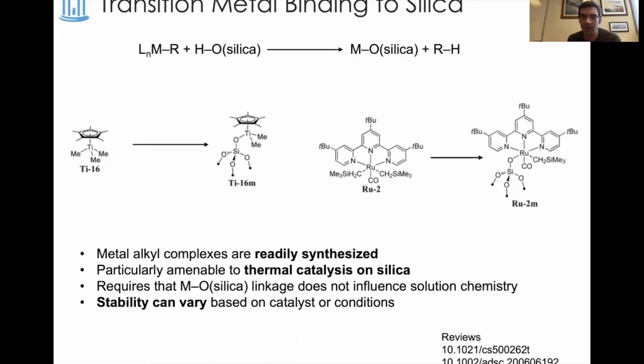The drawback, or potential drawback, is that you need this ligand that's now directly bound to the metal to be amenable to the chemistry that you're interested in. So if your catalyst tolerates an alkoxide ligand in solution, it's reasonable to guess that a linkage like this silicon oxygen bond might be a suitable ligand in a surface catalysis as well. But there's other systems that, once you change the bonding by forming this metal oxygen bond, you may shut down whatever homogeneous catalysis you had seen previously.